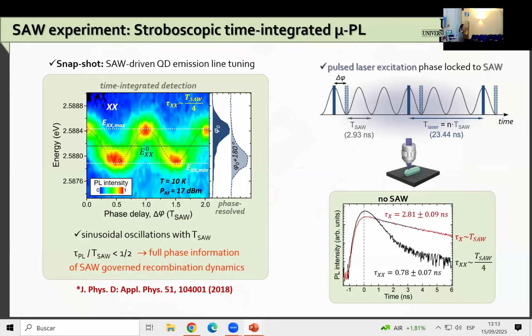If we are measuring time integrated just with the CCD camera, we see this apparent splitting of the QD line, and then suddenly we don't see it anymore while we apply the acoustic wave. And then if we stop applying the acoustic wave, after some time it would again appear. So it seems that basically there's a slight rotation of the flake due to the propagation of the acoustic wave. But once the wave is not propagating, it typically can go back to the initial conditions. Yeah, so it's just a mechanical effect.